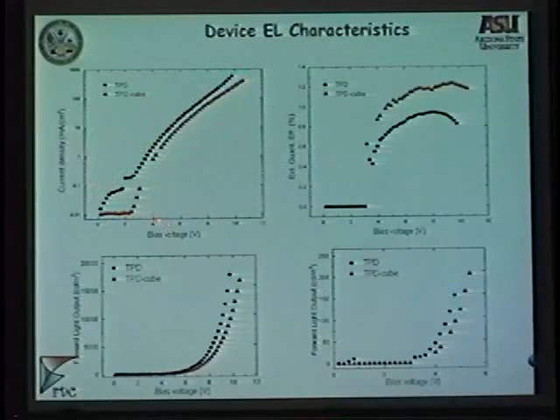And this is the current density. You could see that because of the inclusion of the insulating nanocore in these materials, you would expect the charge to be less free to go from one place to another. So these introduce an insulating barrier basically. However, this is very much needed for OLEDs because you want to cut down on the hole current, because they originally are very high hole mobility materials. So you don't have a balance at the interface between electrons and holes to form excitons.